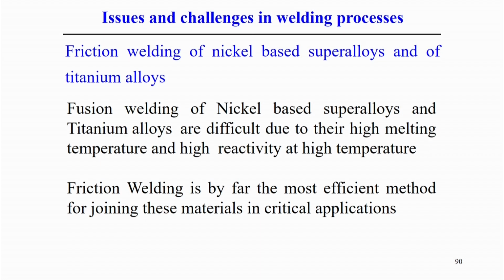Another issue in welding is the friction welding of nickel based super alloy and titanium alloy. For this type of material we generally use friction welding. Fusion welding of nickel based super alloy and titanium alloy is very difficult because of their high melting temperature and, at the same time, high reactivity at very high temperature. That is the limitation of the fusion welding process. So friction welding is the most efficient method for joining these materials in very critical applications, probably in the aerospace industry.